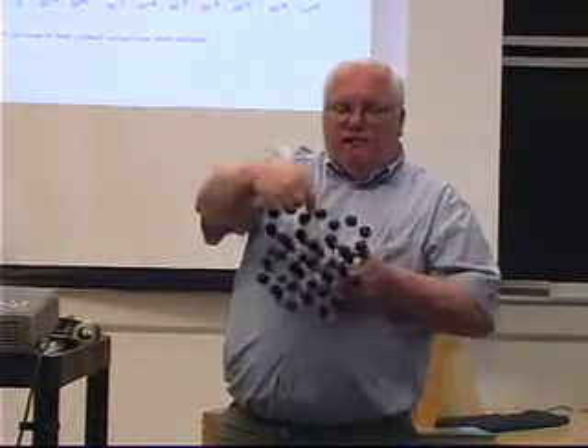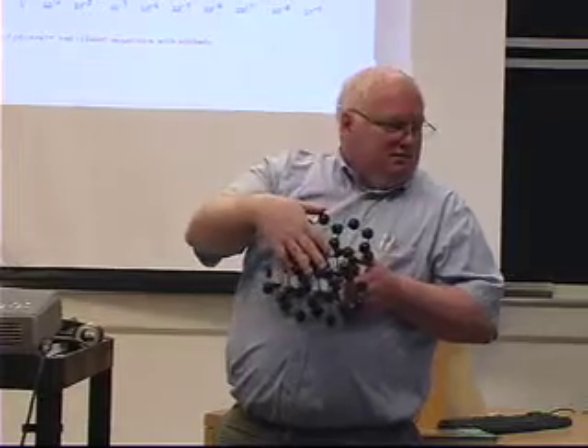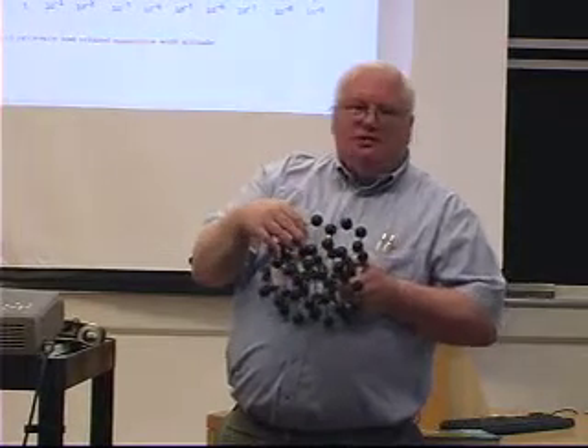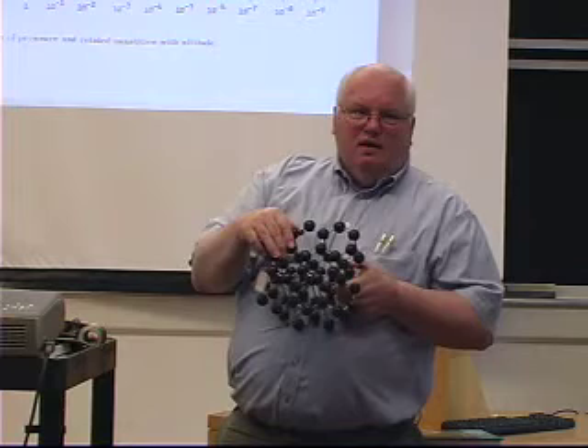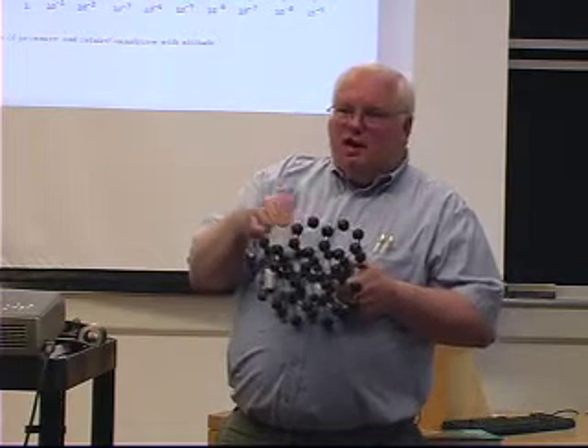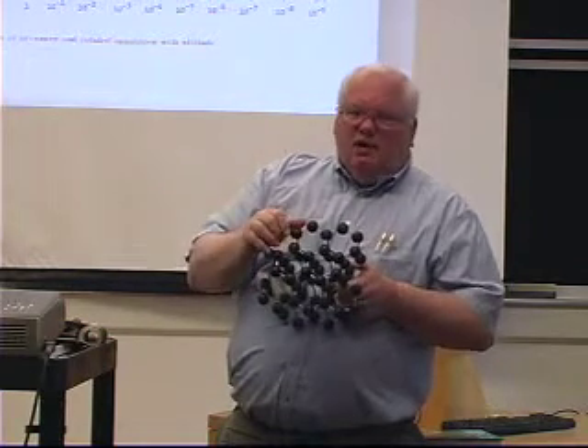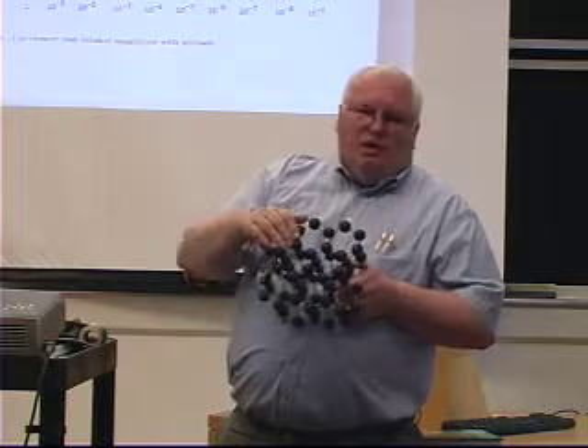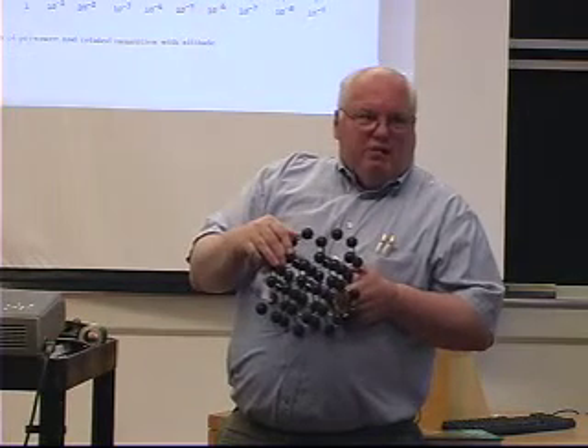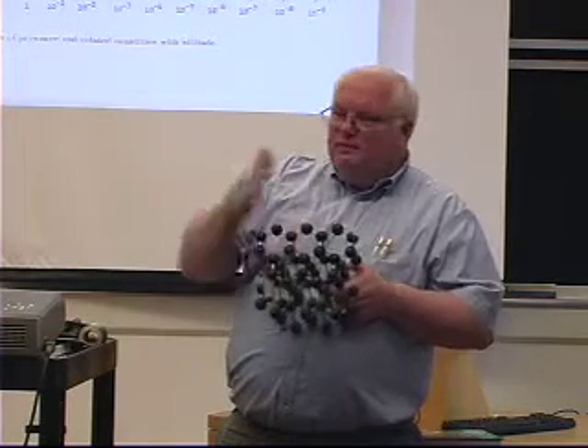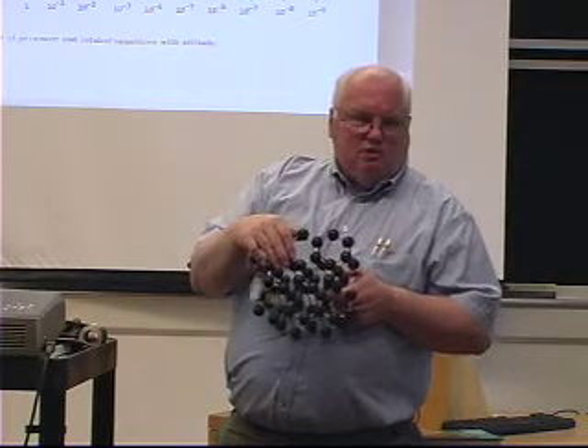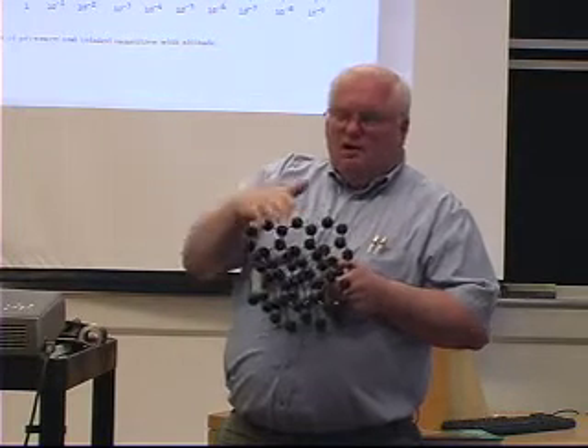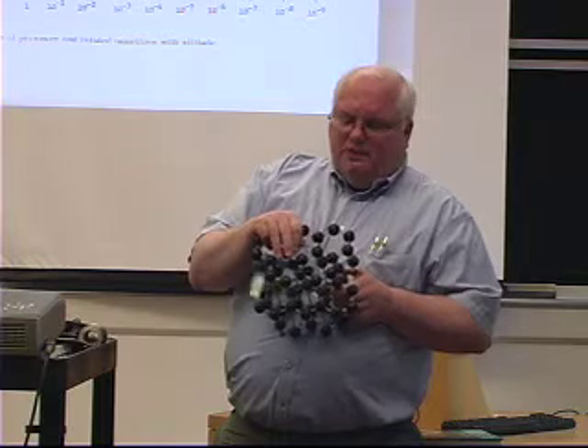But in fact, it has sulfur on the surface. It comes with its own sulfur. Tungsten disulfide, tantalum disulfide, they're all lubricants. But moly disulfide is the least expensive, and it's used as a high temperature lubricant, and the sulfur doesn't evaporate off in vacuums. The molybdenum sulfur bond's much stronger than that chemisorbed carbon oxygen bond.